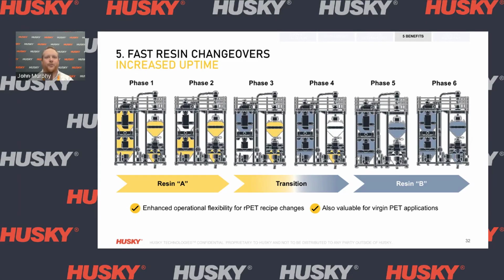If we look on the screen here, I'll walk you through from the left side to the right side to better illustrate what's happening to create this fast resin changeover. Starting from the left-hand side, we can see that we are processing a material, this gold type of material. As we want to switch materials, we don't end up removing all the material from the vacuum dryer. We can keep running that production into the injection molding machine. And because we have 4 distinct phases, we're able to start loading the new material, which is this blue material, resin B, before we are done production of our first resin A material. What we do is we leave a 1-stage gap, which you can see, to separate the 2 materials. And so that results in around 2 hours of resin changeover time, just being that gap between the 2 different types of resin.